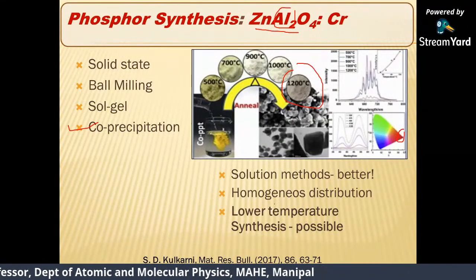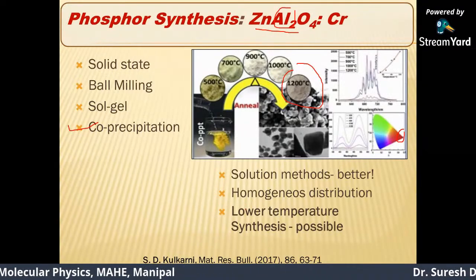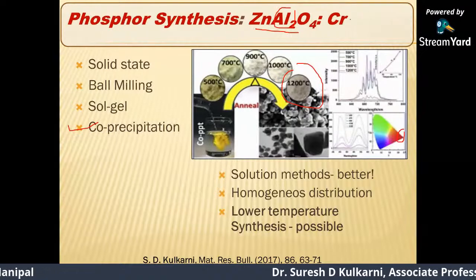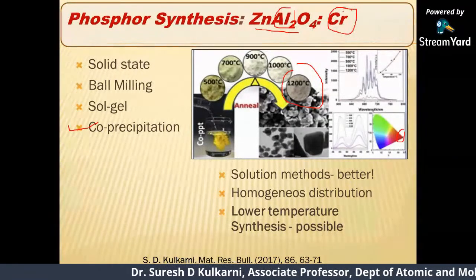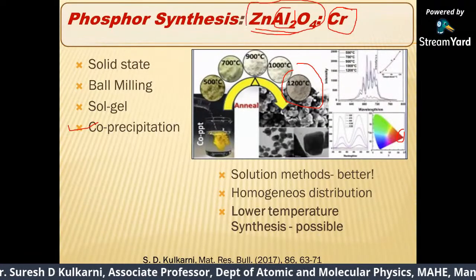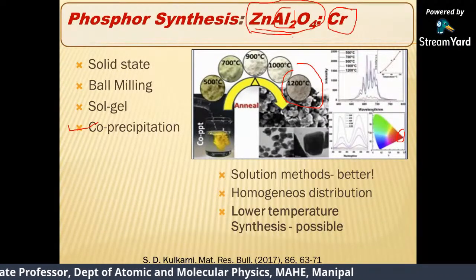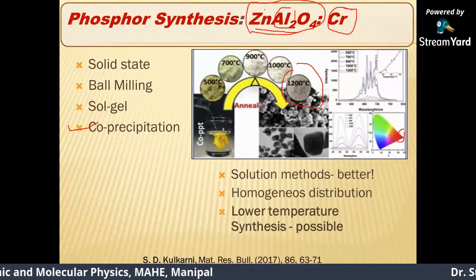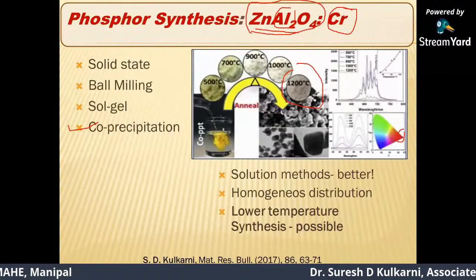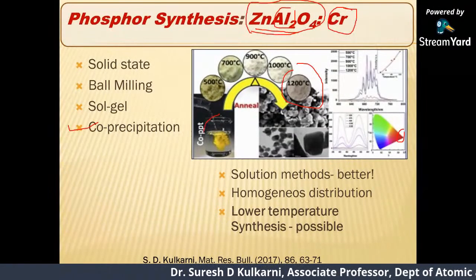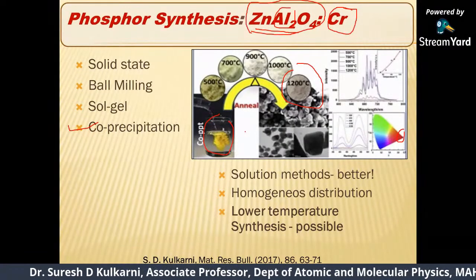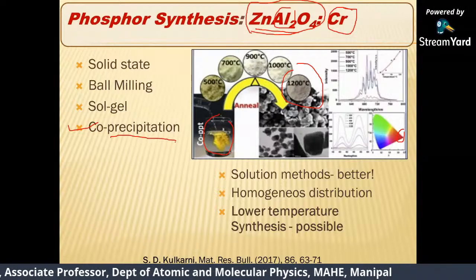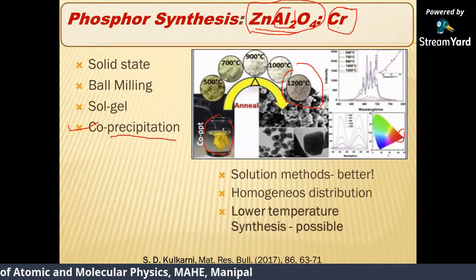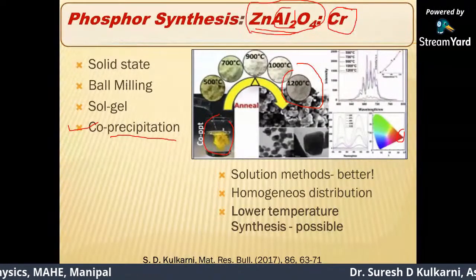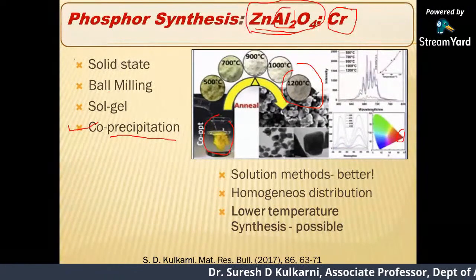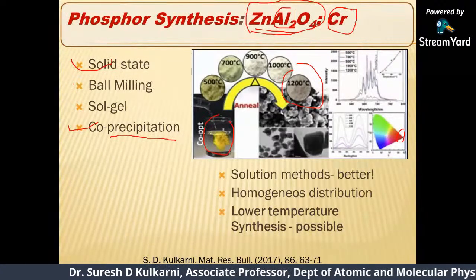One is the solution methods are better. Why do I say solution methods are better? Because the chromium, which is a dopant, can be homogeneously distributed in this zinc aluminate network. We start our synthesis from salts. I start with a zinc salt, an aluminum salt, and a chromium salt. All are dissolved in a beaker in the required ratio, and all of them are precipitated together. Therefore, the distribution of chromium within the host lattice is going to be extremely uniform. You don't get a similar homogeneous distribution in case of solid state or ball milling.